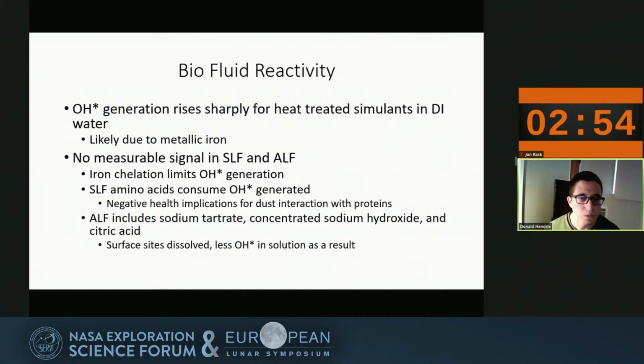In the opposite case, what could be happening is that the amino acids in both of these biological fluids, especially in the SLF, since SLF has more amino acids, are reacting with the OH radical at a rate much faster than that at which the DMPO molecule can trap the OH radical for measurement. So if that's happening, there's no way that we can measure it using EPR. And on top of that, the negative health implication of the OH radical reacting with the amino acid is that since your proteins are made up of amino acids, if you inhale any lunar dust that immediately starts generating massive amounts of OH radical, that's going to interact with all the amino acids that make up your proteins. So then your proteins may start to unfold and denature and lead to a whole bunch of other bad stuff.